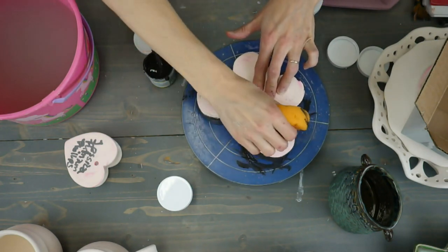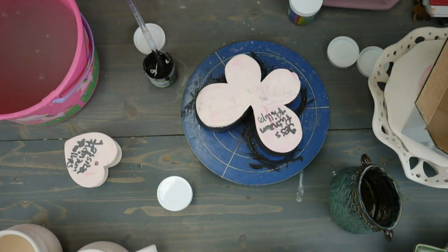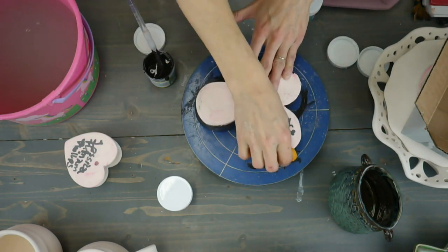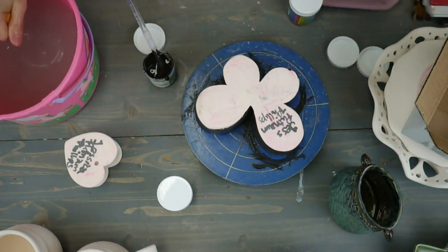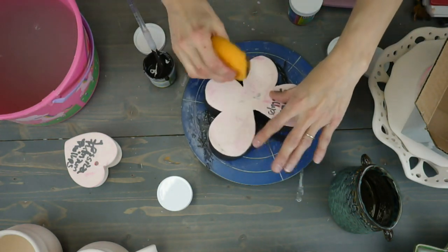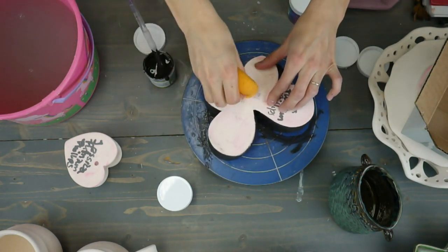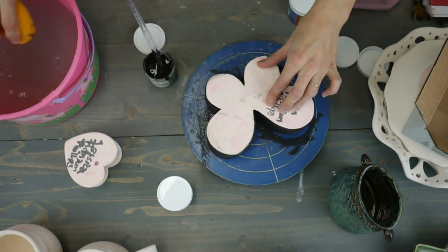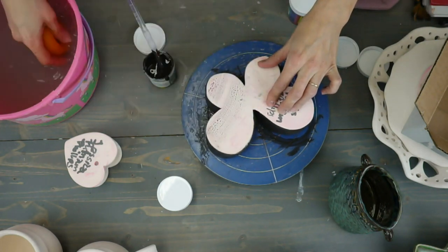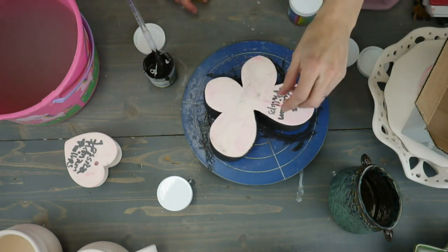That's a good question. So you have a few sets of Amaco velvet underglaze, and you just noticed that a couple of them you haven't used have dried up. Can you reconstitute them? You can. Just add a little bit of water, and then let it set, usually overnight, and check it. If you can stir it, stir it. If it still seems a little too thick, add a tiny bit more water, but you don't wanna add too much water at once because you can make it watery. And then you have to figure out how to get the water out, right? Then you have to let it set and evaporate, and nobody wants to do that. But you can reconstitute them.